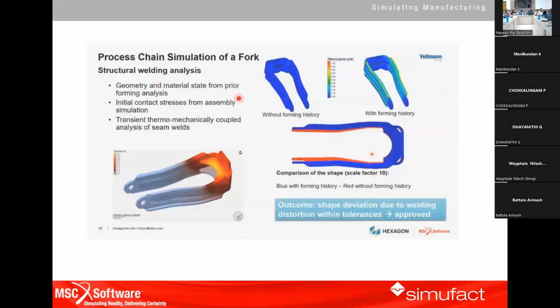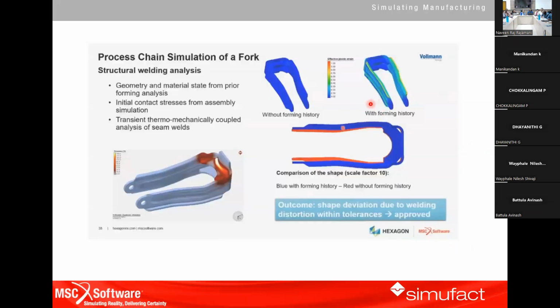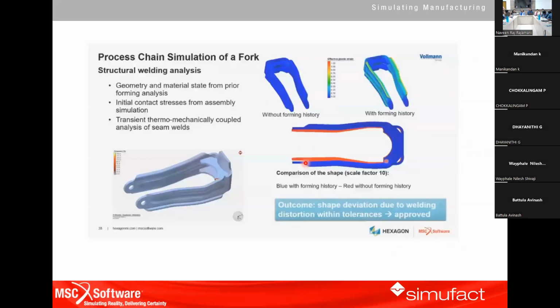So for the welding simulation, for example, if you do a welding simulation with the forming history, some residuals resulting from the forming will be taken into the welding. You can see a comparison here. They have made a comparison with the forming history, the blue one, and without the forming history, the red. You can see the drastic change in the distortions if you are doing the analysis with and without the forming history.